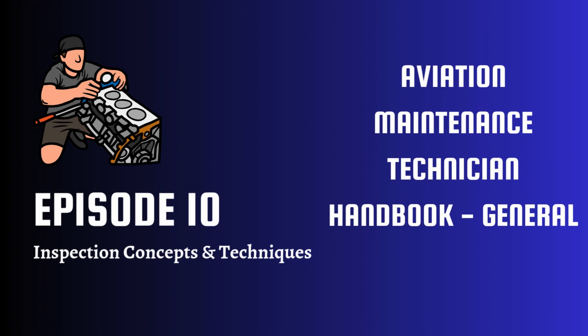Doesn't it need calibration? Absolutely. Like most NDI, accurate eddy current testing requires careful calibration using a reference standard. This standard must be made from the exact same material, alloy, and heat treat condition as the part you're testing, and it must contain known, precisely manufactured flaws like small notches or flat bottom holes of specific sizes to set up the instrument's sensitivity and response correctly before you start inspecting the actual component.